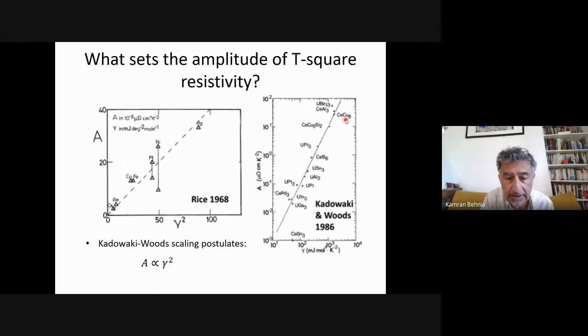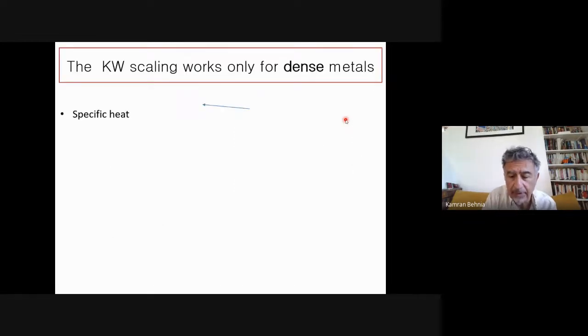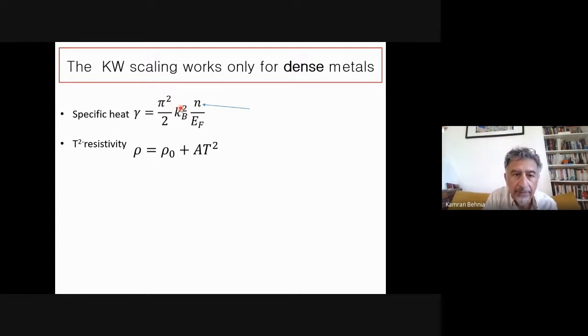So the postulate is that this A term is proportional to gamma square in different materials. Gamma is the T-linear specific heat. Now, one thing you should have in mind, which was only understood very recently, is that this is valid for dense metals. The reason this scaling works roughly is that for a Fermi liquid, you can write your T-linear specific heat in this way. It is proportional to Boltzmann constant squared and the ratio of carrier density to the Fermi energy.